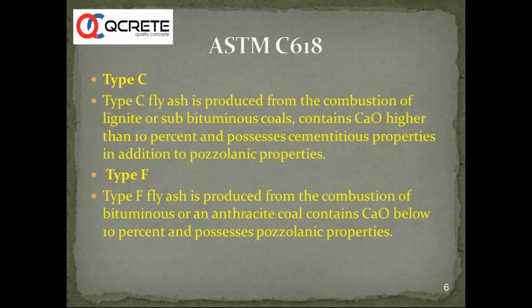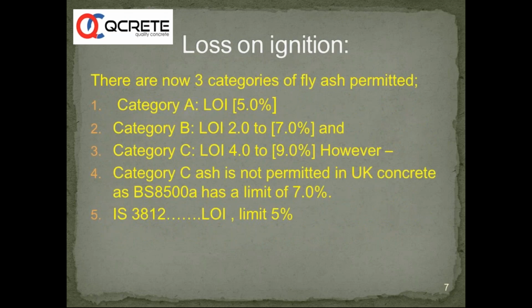And so a lot of work has been done in India on Class F fly ash. There is also another one called Class N fly ash, where N stands for natural, as per ASTM C618. BS 8500 has other categories where they have classified fly ash based on loss on ignition. Loss on ignition is an important property, where the loss on ignition determines how much superplasticizer or admixture is required, and this LOI also affects the air entrainment properties.